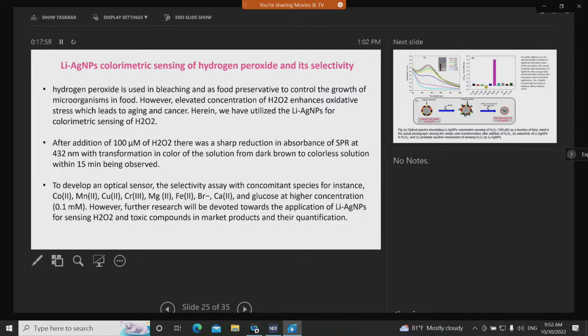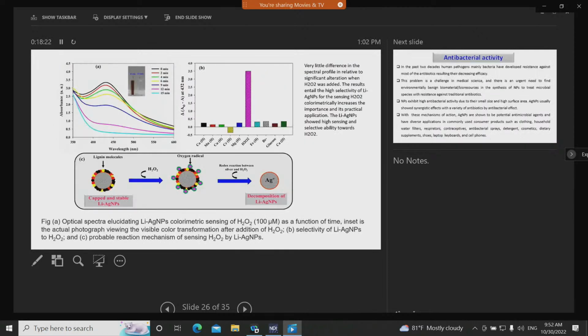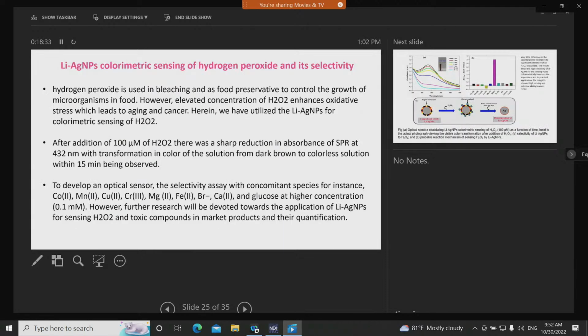So here we have utilized the LiAgNPs for colorimetric sensing of H2O2, and we know that colorimetric sensing is a very easy way to find out the sensing of H2O2. After addition of the H2O2, we could see there was a sharp reduction in absorbance of SPR at 432 nanometer, with transformation in color of the solution from dark brown to colorless, with a decrease in the absorption spectrum bands within 15 minutes, which increases the applicability of the lignin silver nanoparticles.